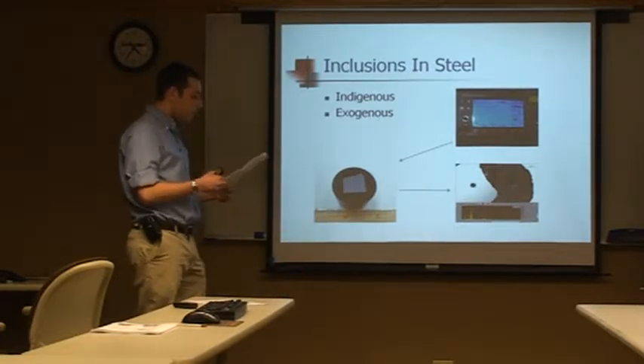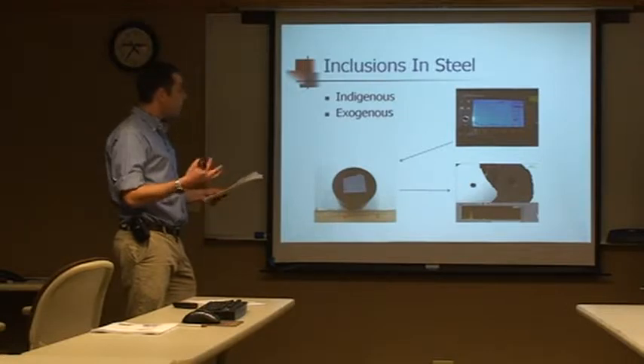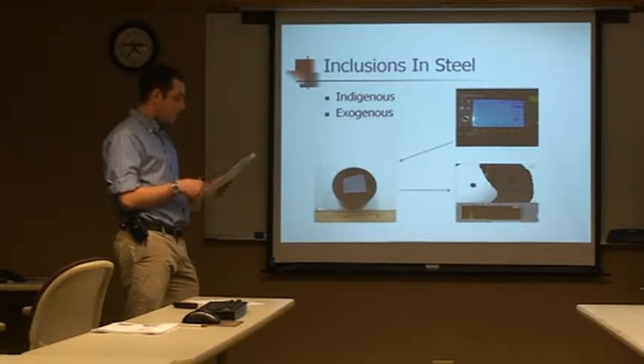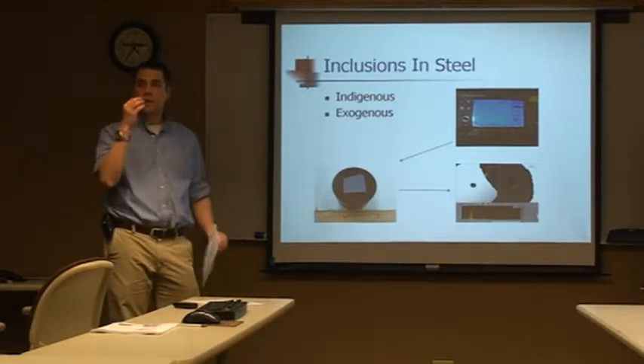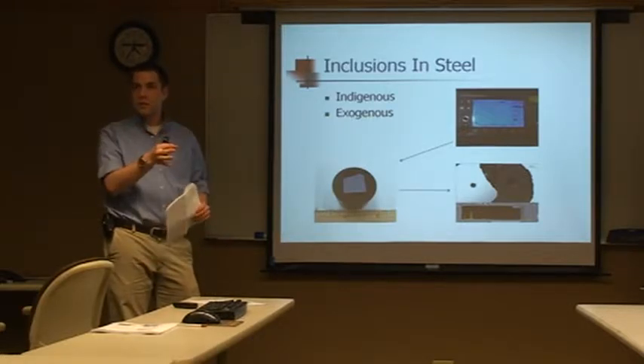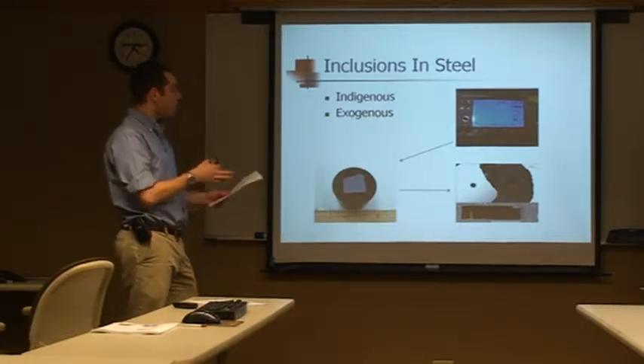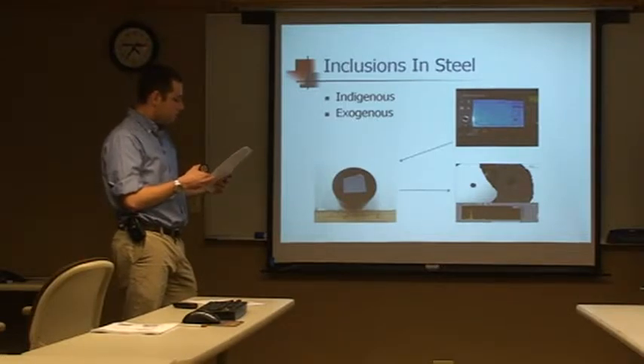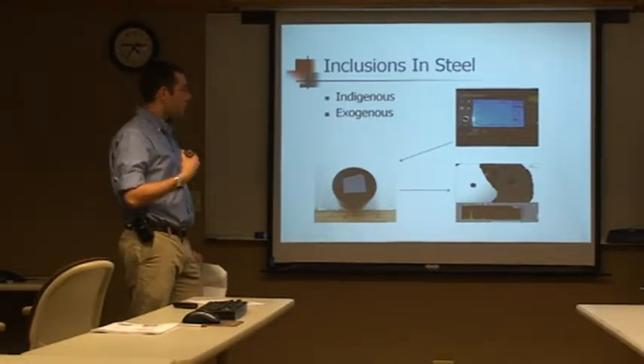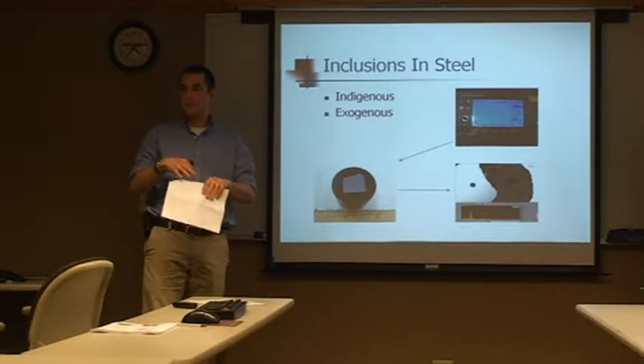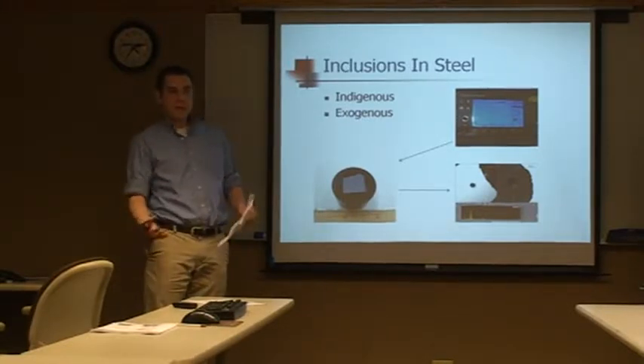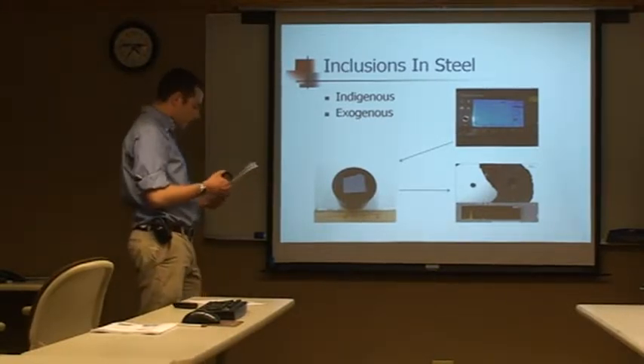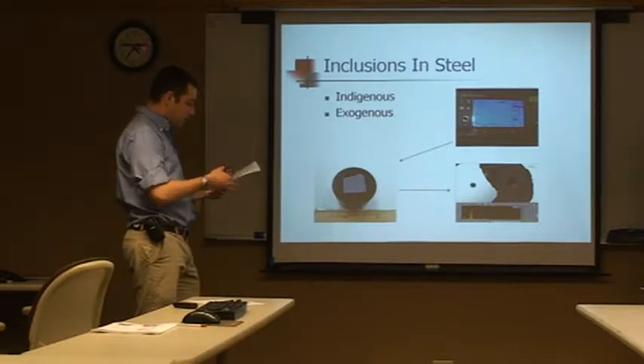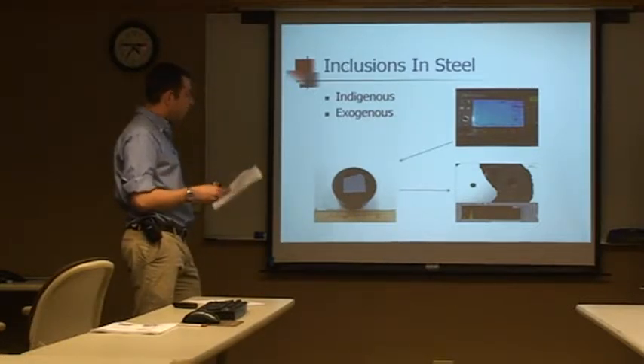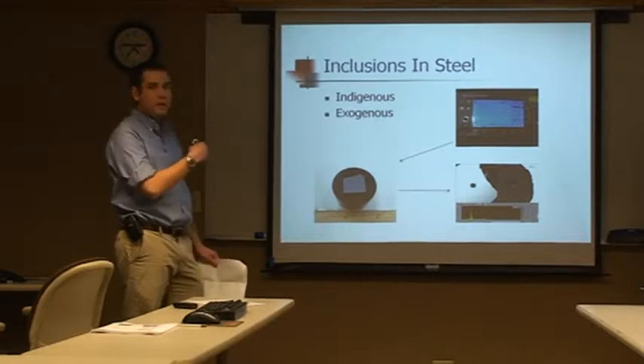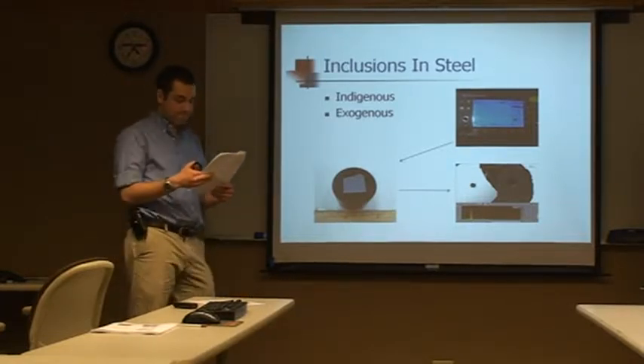Some common types that we've seen are refractory product from the stuff that lines the ladle and the runner bars, teeming flux, which is a powder lubricant we use in the molds to keep the steel from sticking as it rises up through the mold, and the nozzle sand that we have in the ladle to protect our slide gate.